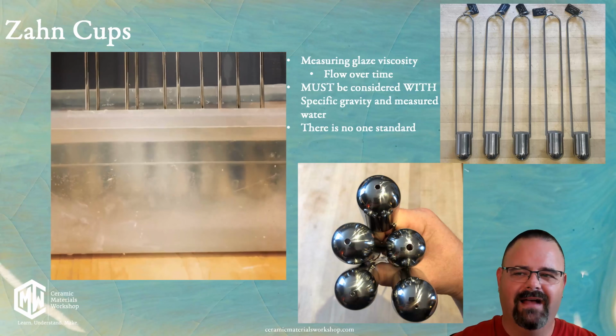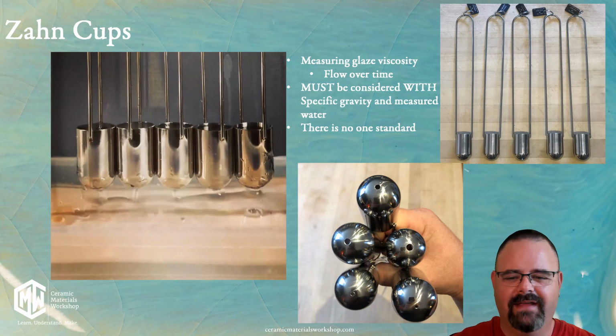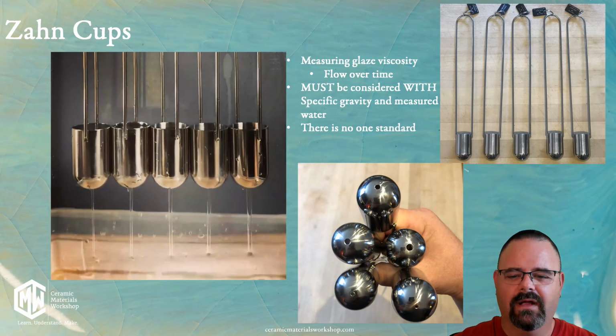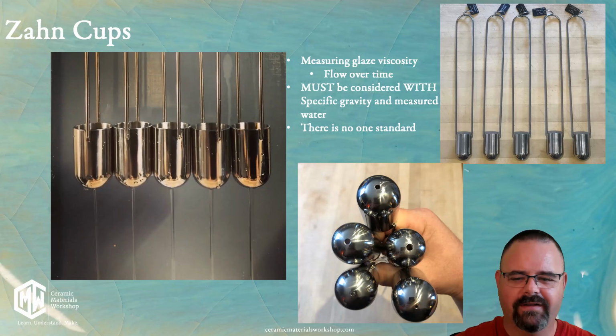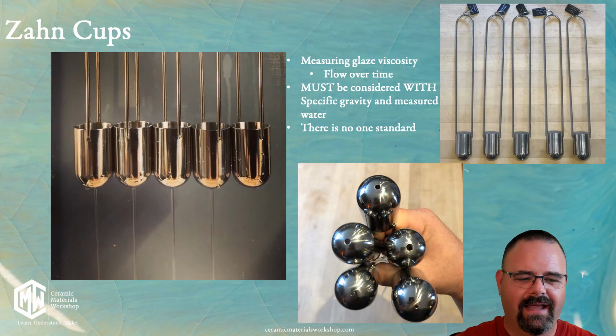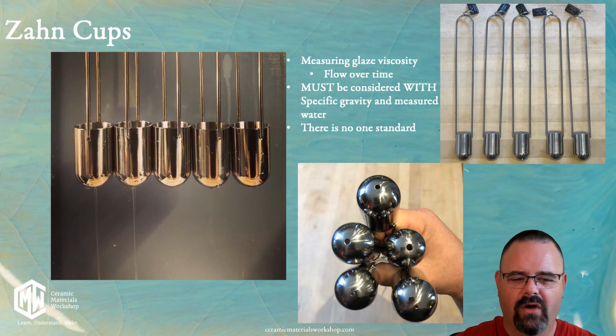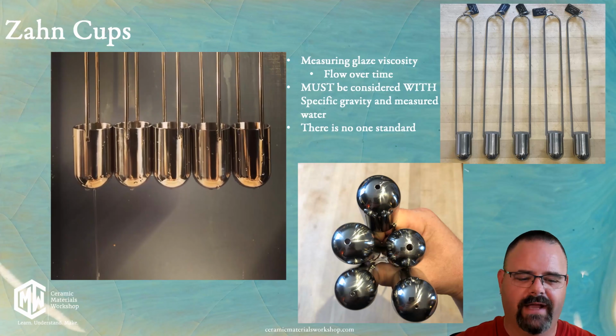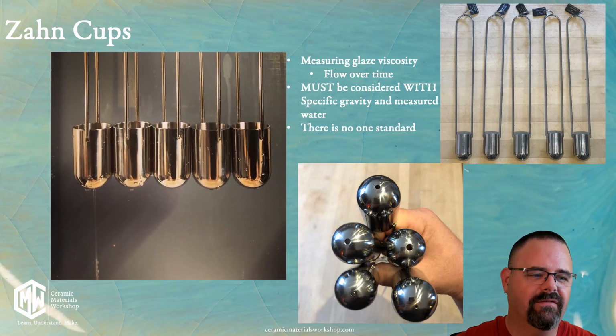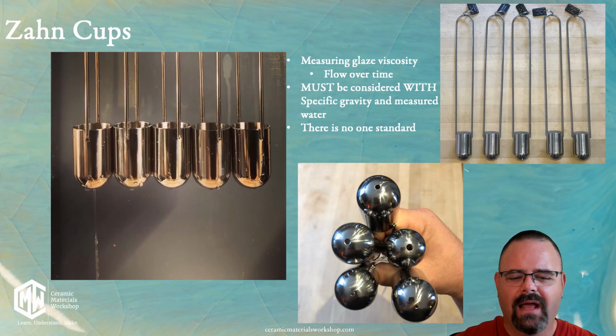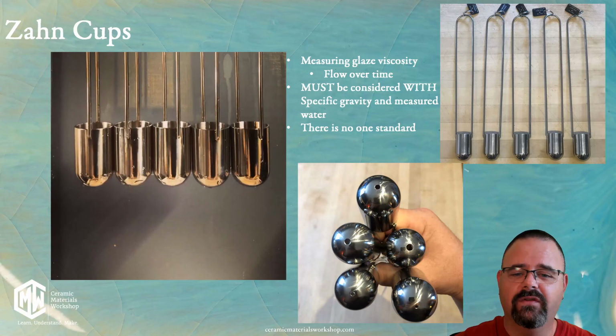Viscosity is measured with a Zahn cup or a Ford cup, and this is an example of some Zahn cups at work. These are 5 different Zahn cups that we have, and each Zahn cup has a different diameter hole, as you can see down at the bottom. They're labeled from number 1 to number 5, and they all work the same way. Basically, when the hole is small, the water drains very, very slowly. When the hole is big, it drains very, very quickly. Now, you can use any of these. The metric that you use is very simple.